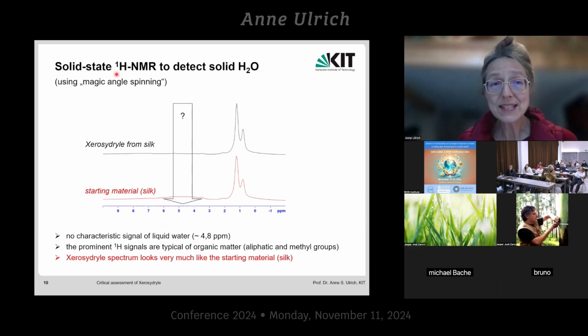I told you we used solid state NMR, special magic angle spinning techniques, looking at the Xerosydryle derived from silk, sample from Naples. And we were expecting to see proton signals in a water-like environment near a shift of 4 to 5 ppm. That's where you would usually see proton signals in water, liquid water, ice, etc. But there was not much. There was hardly anything. A bit broad here. But remarkably, we see here signals of aliphatic and methyl groups. Interestingly, these signals are both in the Xerosydryle sample, but also in the starting material. So in fact, these two spectra look very similar. So we were wondering maybe some of the starting material made it into our Xerosydryle sample.